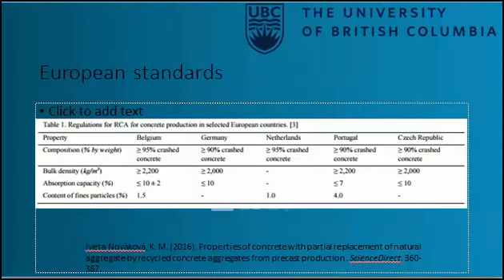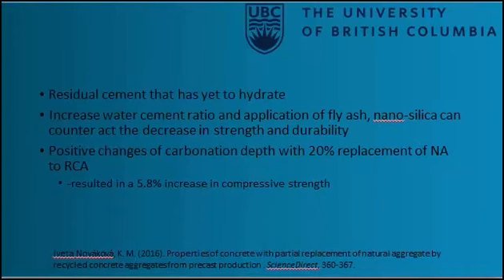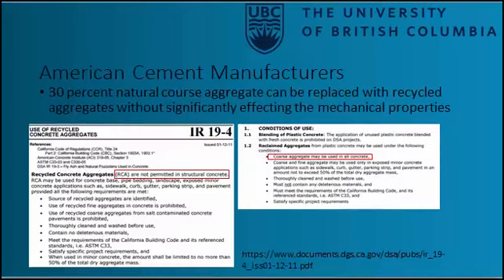One study found that the European countries have standards for over 90% concrete in their mix, where others are 95%. This could be 5% other. The study also found that residual cement was left over in the recycled concrete, which created complications during the mix design. Increasing the water-cement ratio in conjunction with the addition of fly ash and nanosilica will counteract a decrease in strength and durability. It was found that a 20% replacement of coarse aggregate with recycled concrete aggregate would increase carbonation depth and increase compressive strength by 5.8%. An American standard found that 30% replacement of natural aggregates resulted in little effect on mechanical properties.